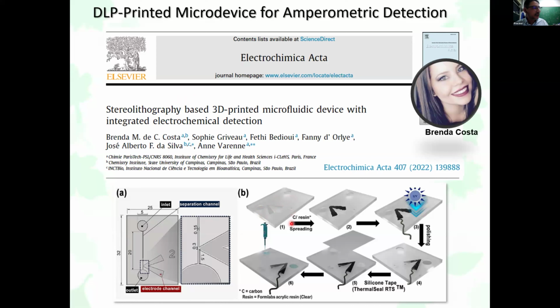And the 3D printing, again, can be used to prepare this kind of grooves. Brenda worked on this project. Brenda filled these grooves with conductive pastes, the same resin used to print the device. Brenda introduced some carbon material in this resin, and you can prepare a conductive solid material using basically the same material of the printing device.